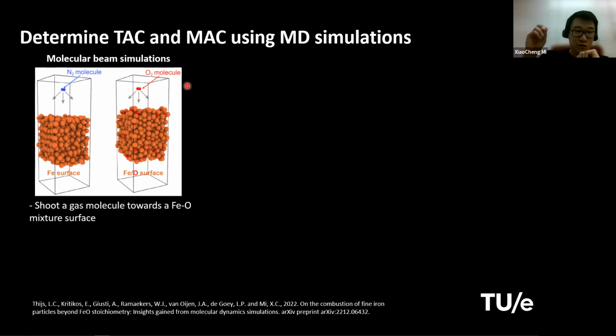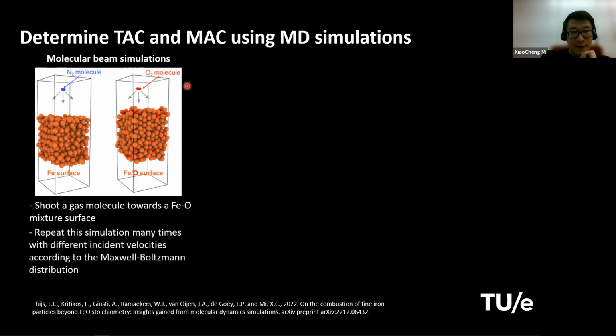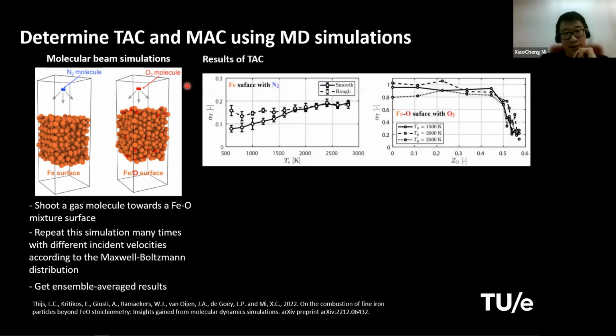And the idea is you shoot one single molecule towards this surface, and then you can measure whether it is absorbed into the surface and what is the energy exchanged before and after the collision, right? And after you repeat this simulation many times with different incident velocities of the molecules according to a certain Maxwell-Boltzmann distribution, you can obtain this ensemble statistical average result for MAC and TAC, right? So here are some results.